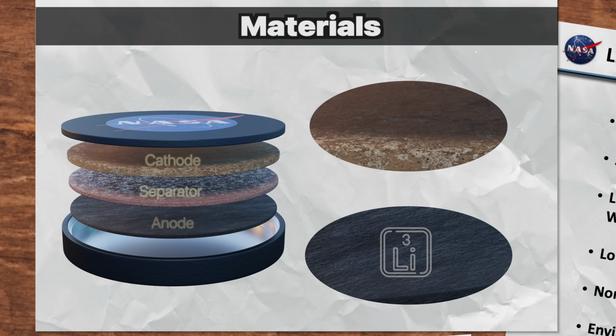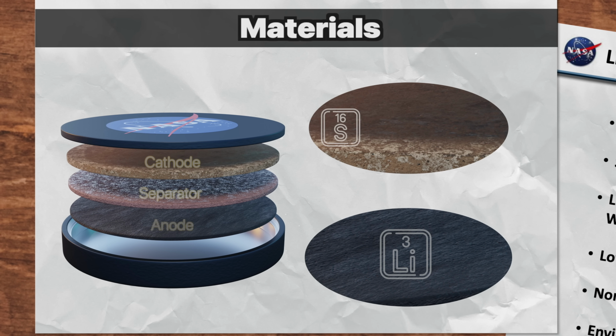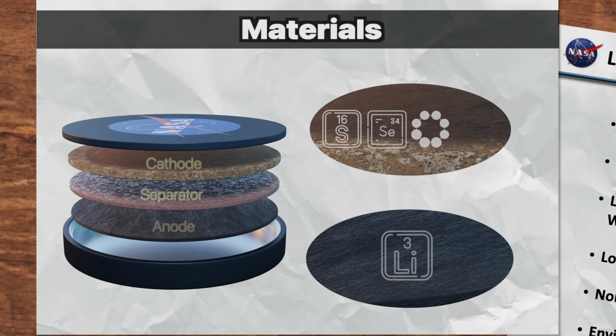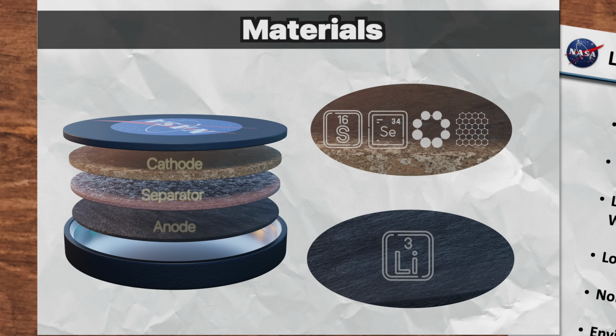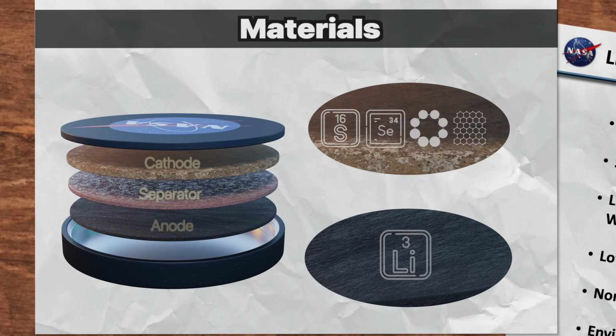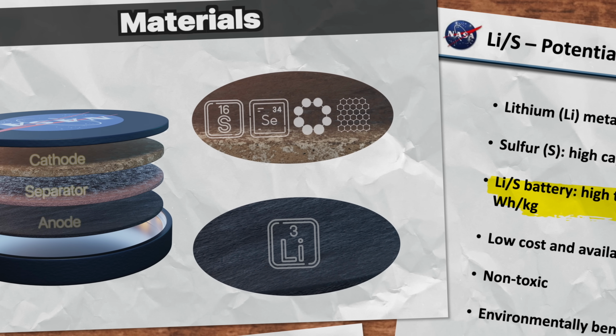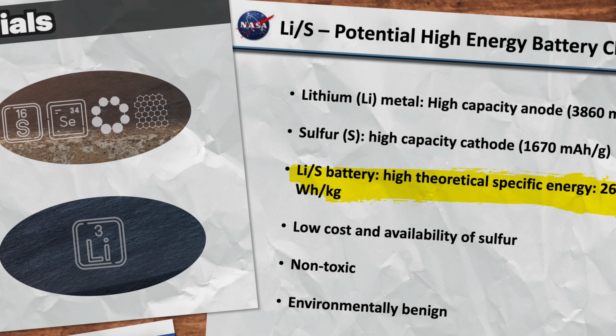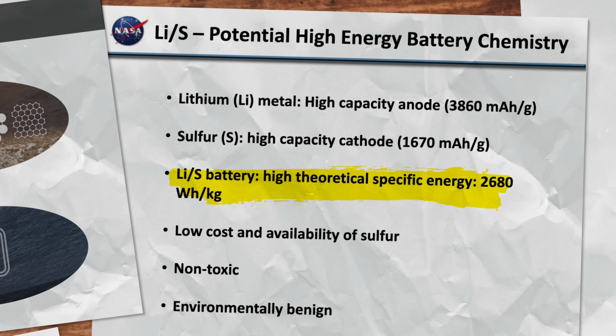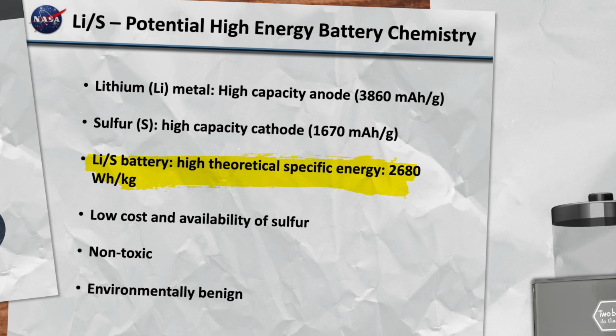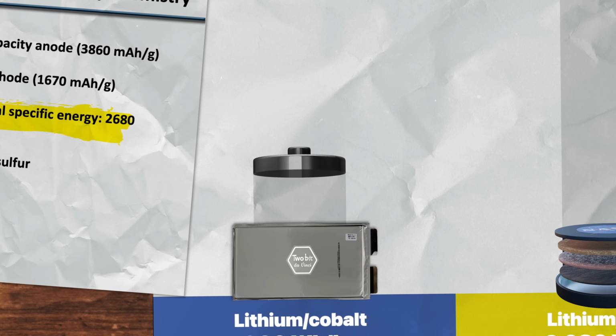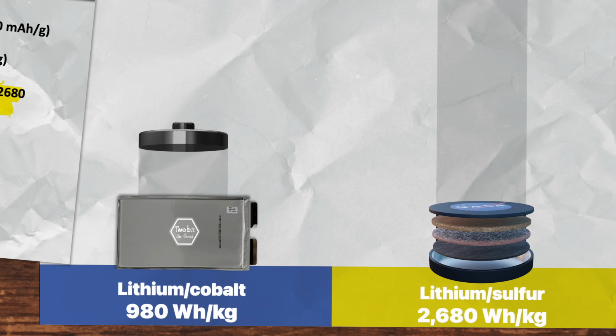The cathode is a bit more complex. It's made of a combination of sulfur, selenium sulfide compounds, and a patented porous graphene called holey graphene. They chose the lithium-sulfur chemistry because it has a very high theoretical specific energy of 2,680 watt-hours per kilogram, which is almost 3 times that of lithium cobalt oxide batteries, which is approximately 980 watt-hours per kilogram.